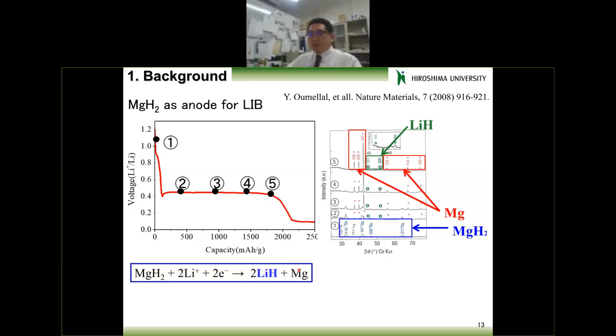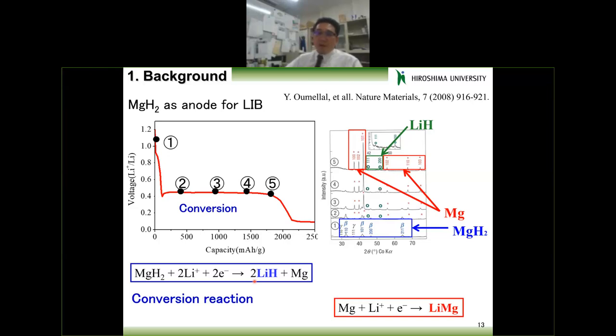Of course, in the case of graphite, lithium can be intercalated into graphite. But in this case, a new hydride was generated. So we call this a conversion reaction for lithium-ion batteries. And the second plateau is something like this. They reported that magnesium reacts with lithium ion, and then a lithium magnesium alloy was generated. That was slightly long time ago that they focused on magnesium hydride as an anode for lithium-ion batteries.